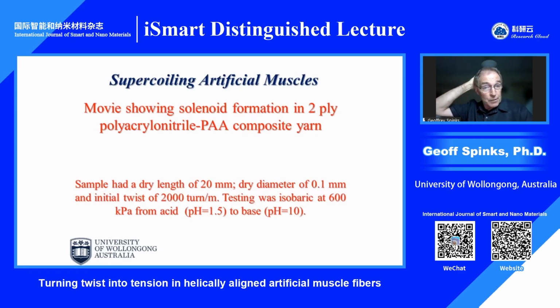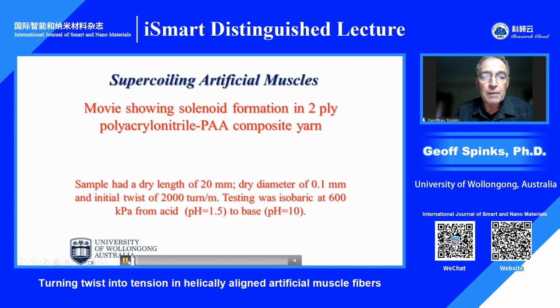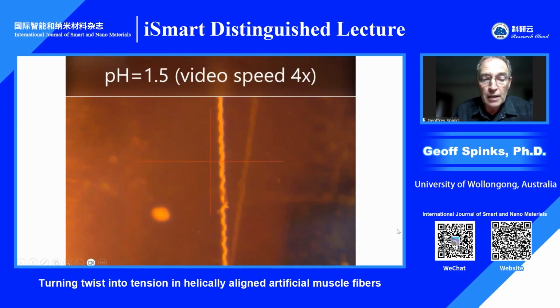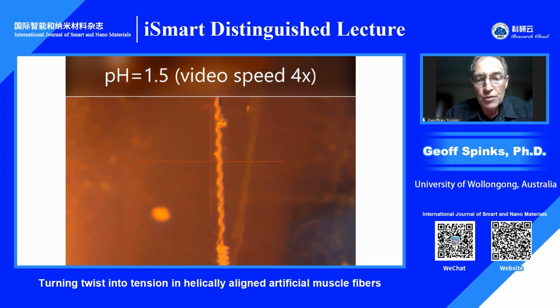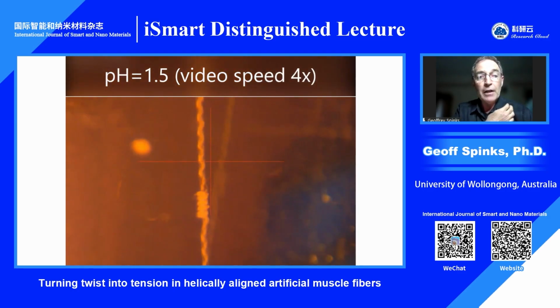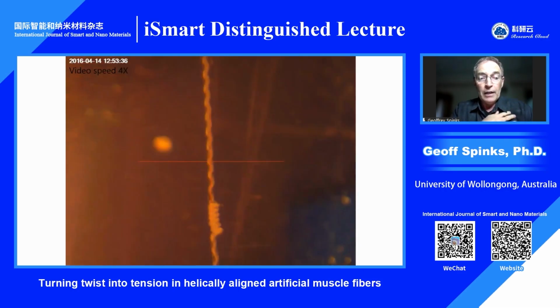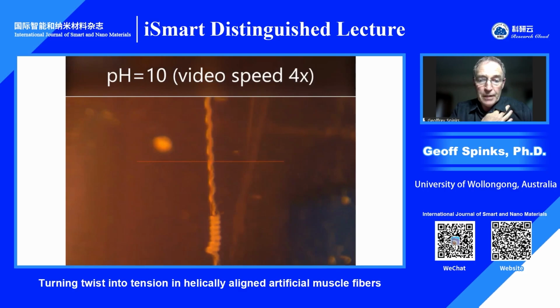The polyacrylonitrile gives us some strength. Now the polyacrylic acid is really what gives the swelling ability, particularly in base solution. And you can see some really lovely solenoidal type supercoils forming in this sample due to the swelling. A stack of solenoid supercoils occurring just at the bottom of this frame. Now that's swollen in acid. We now immerse the same sample in base, and the process continues. So, and you can almost see the twist being relieved out of the fiber as the coils form. And that's what's driving the supercoiling process.